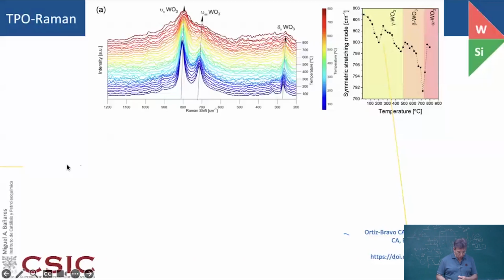If you look at it with Raman, you can also see a similar story. You are heating the tungsten on silica. Here you have basically that you get the gamma phase of a tungsten oxide that goes into the beta phase and into the alpha phase. That's it, because this is only tungsten on silica, so nothing else happens.